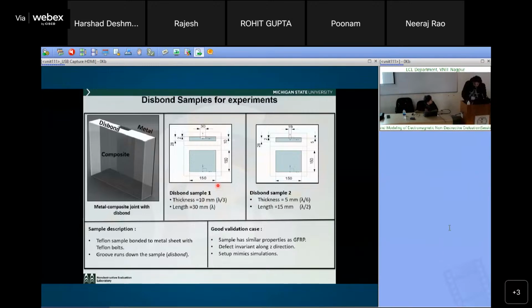We have done defect detection of GFRP using microwave in our lab. Defects included are mild steel, aluminum foil, and Teflon tape. We could only detect the metallic defects. Why? Well, it depends on what frequency they use, right? Was it far field? Was it near field? The reflector, metallic foil, will probably produce a very strong signal. But if the defects are less than a wavelength, and if you did far field, you'll not be able to detect it. So it depends on